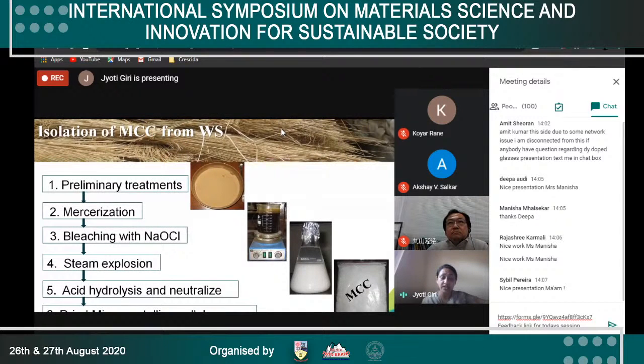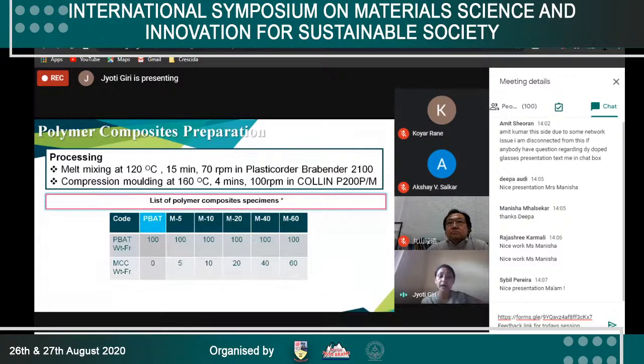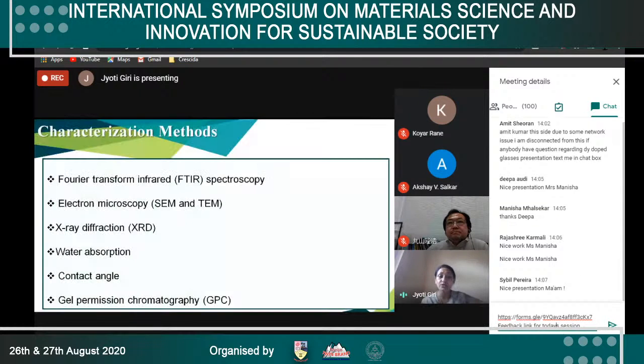The isolation of the microcrystalline cellulose from wheat straw is done by a series of thermochemical mechanical processes, and the extracted MCC is compounded by melt mixing with the polymer matrix PBAT, and different compositions of MCC are kept in the composites as shown in the table. These composites were characterized by different characterization tools. The results of the characterization are shown here.